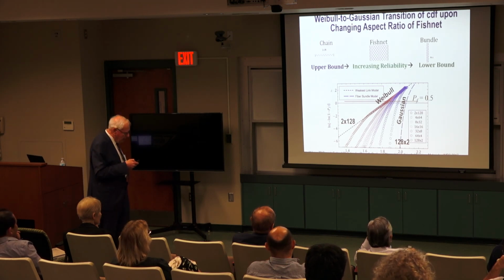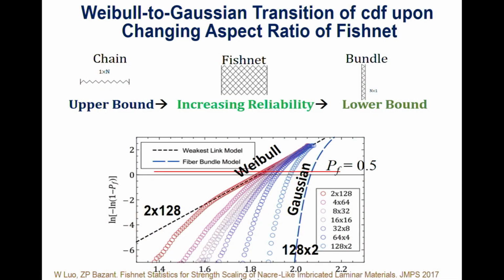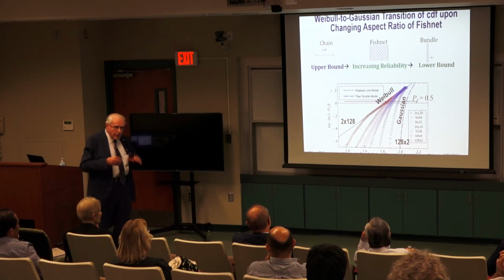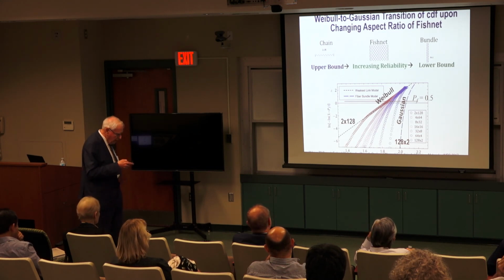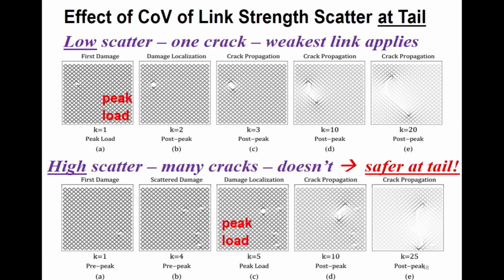Now it has been done very carefully computationally when Luo did it. Each point is 10,000 simulations, and here we move from 2 times 128 to 128 times 2, from chain to bundle, and you see this continuous transition. It is not a superposition of these two simulations. It's much more. It's very different actually. If you would try a partition of unity combination of these two distributions, it would be incorrect. It will be very different.